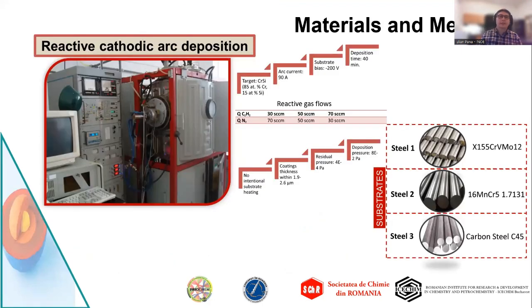To achieve our objectives, we employed reactive cathodic arc deposition to obtain chromium silicon carbonitride coatings. We used 3 different steel substrates with different iron to carbon ratios, and obtained 3 different carbonitride coatings under 3 different reactive gas flows that we can see here: 30 to 70, 50 to 50, and 70 to 30. We included some silicon in our layers by using composite targets formed of chromium and silicon.